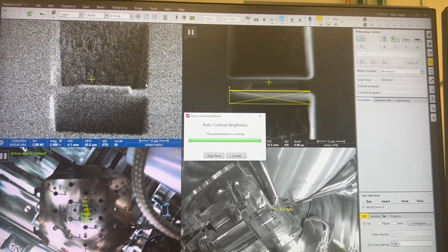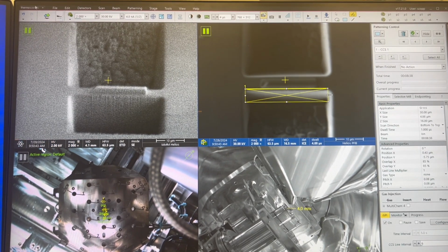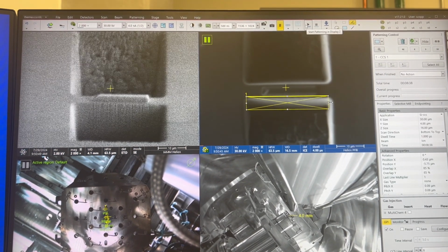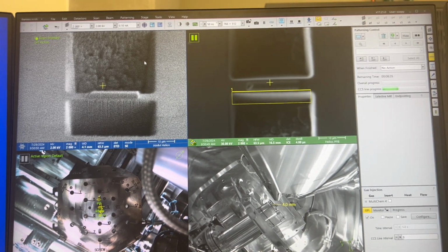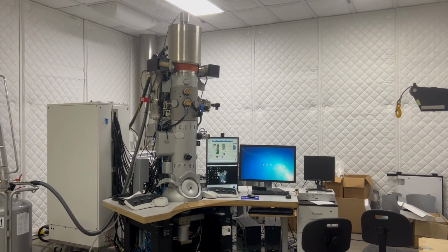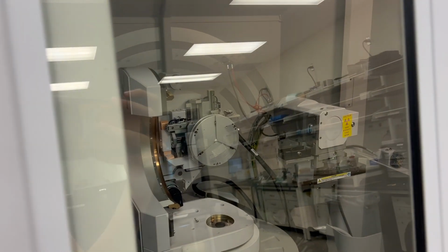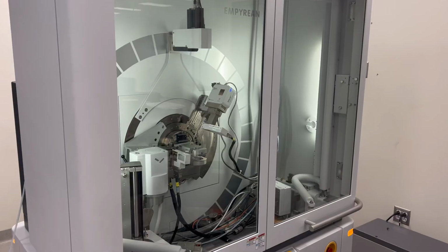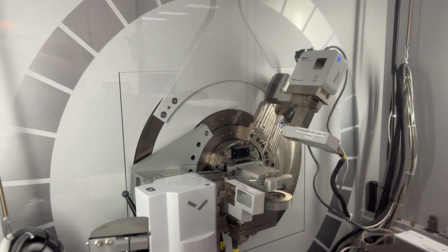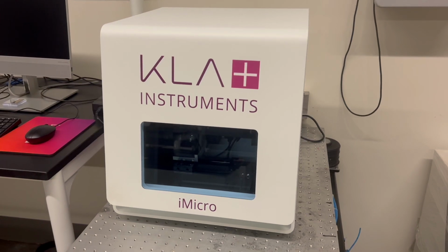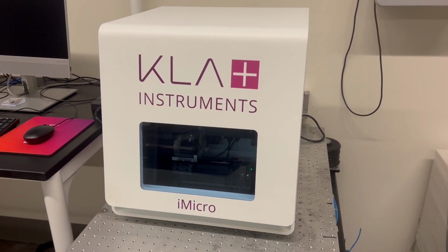Using a focused ion beam, or FIB, we can lift out nanometer scale samples from the bulk material that will later be used for characterization in a transmission electron microscope, where we can do atomic resolution imaging and also image any small-scaled features from radiation damage. X-ray diffraction can be used to analyze the physical properties of the material, such as phase composition, crystal structure, and material orientation. Lastly, we can use nanoindentation to test the mechanical properties of our material.